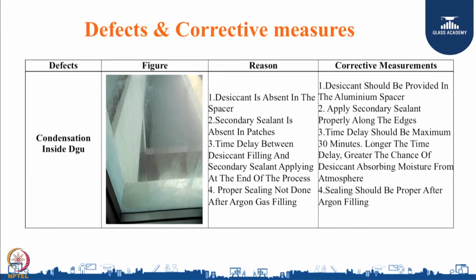Condensation inside DGU. Desiccant is absent in the spacer. Secondary sealant is absent in patches. Time delay between desiccant filling and secondary sealant applying at the end of the process. Proper sealing not done after argon gas filling. Corrective action is desiccant should be provided in the aluminum spacer. Apply secondary sealant properly along the edges. Time delay should be maximum 30 minutes. Longer the time delay, greater the chance of desiccant absorbing moisture from the atmosphere. Sealing should be proper after argon filling.